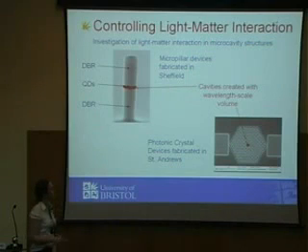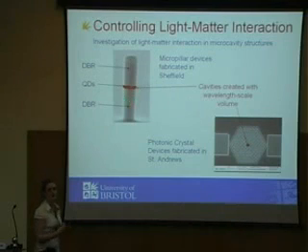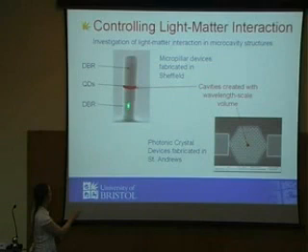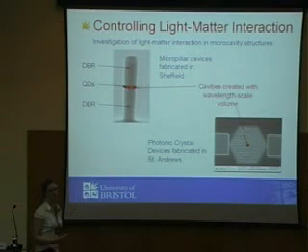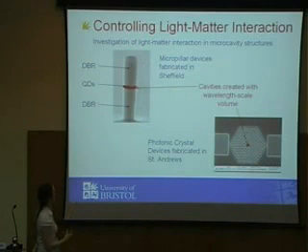We have a micropillar device, and this was fabricated in Sheffield. Here we have a system with distributed Bragg reflectors, which essentially act as mirrors. They reflect the light downwards and upwards here. In fact, we've created a small cavity here, which I've coloured in red. This cavity contains the light over a very small volume, about 1 micron across and about 10 microns in height.